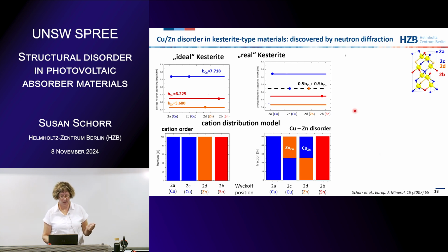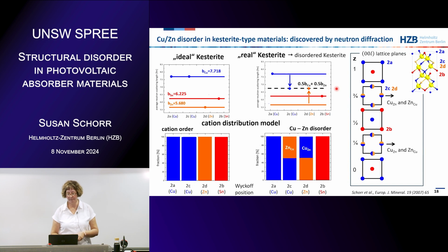And I thought I would get a figure like that. So I would have the two points for the copper site on the blue line, on the copper neutron scattering length, the tin on the tin neutron scattering length, and for the zinc site here. But what I got was something like that. And this puzzled me a lot in the beginning, because for the 2C site, the value was much lower than the neutron scattering length of copper, and for the zinc site, it was much higher. It was in principle on a level of half-half neutron scattering length of copper and zinc. And this was the first hint for the copper-zinc disorder.